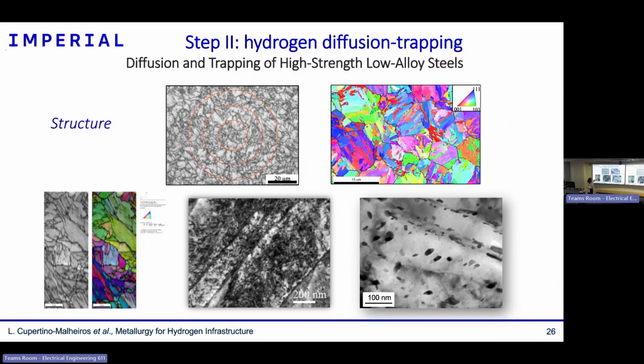In these colorful diagrams, what is shown are grains. Metals have lots of crystals with different orientations, and each of these colors is one orientation. Here, what you can see are dislocations. You can see lots of black lines, and these steels have lots of them because they are quite strong. You can also see lots of particles. Those are carbides, second phase particles, where hydrogen can also accumulate.